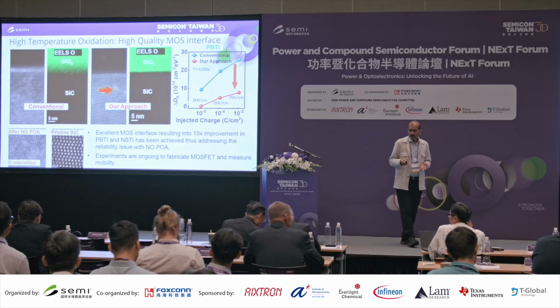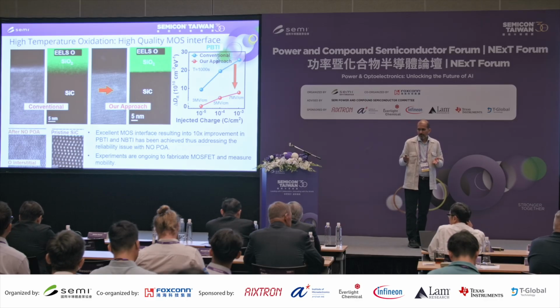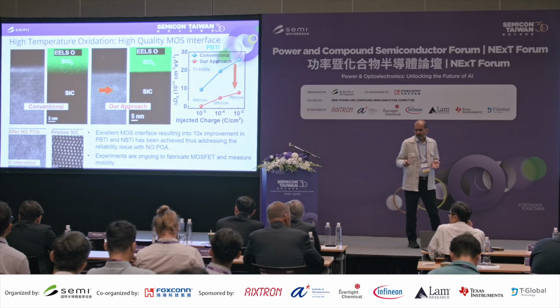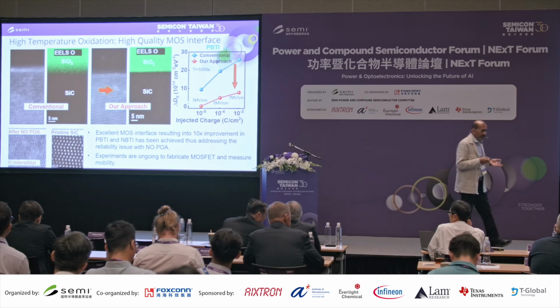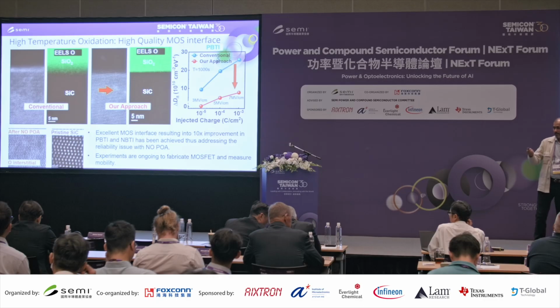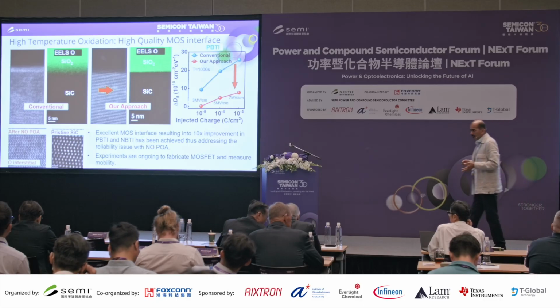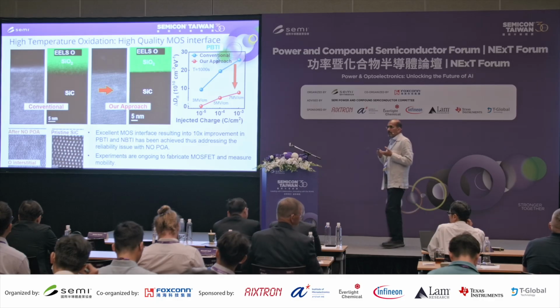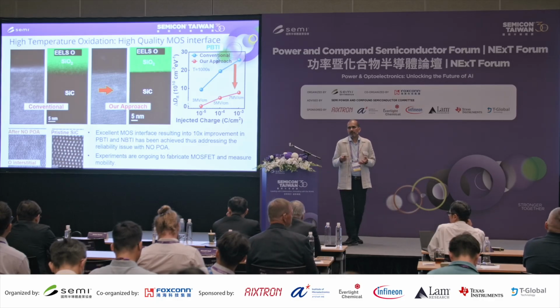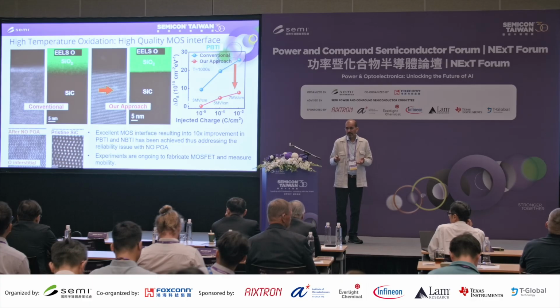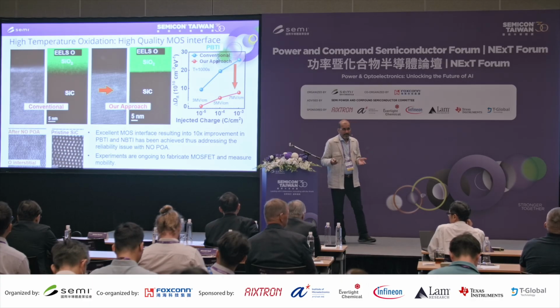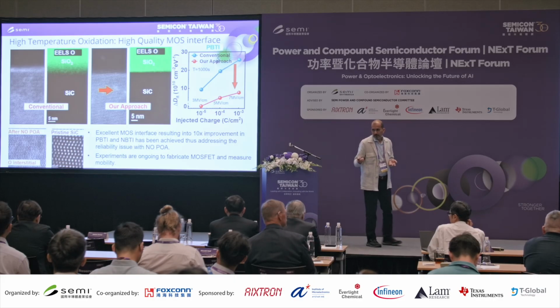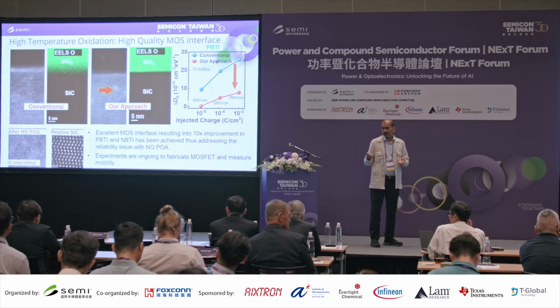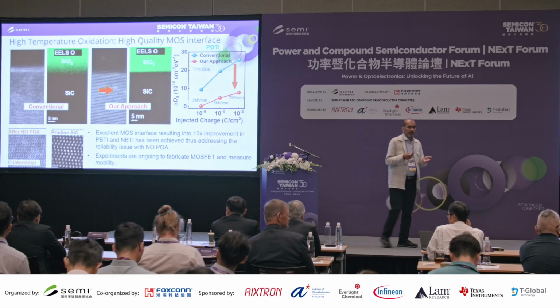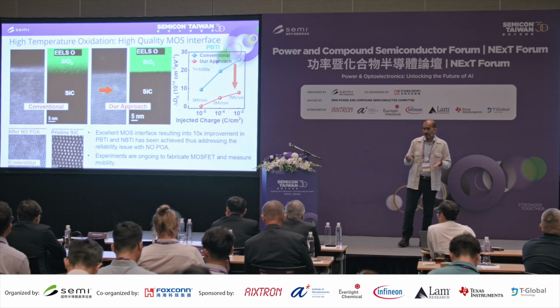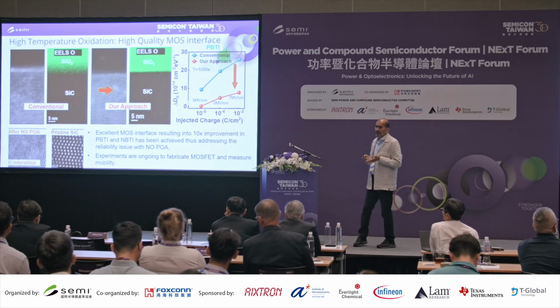Look on the left, and pay particular attention to the high resolution TEM and EELS pictures. The interface with the conventional way of doing oxidation, NO POA, or even deposition is very, very blurred. By doing a post-treatment, we have recovered the interface to be absolutely very sharp. You can see there is no oxygen now in the silicon carbide using our approach. And that is able to solve the BTI problem. Clearly, there is a 10x improvement in PBTI here, and similar improvement is shown in NBTI. So with this process we will have very good mobility along with good BTI performance.